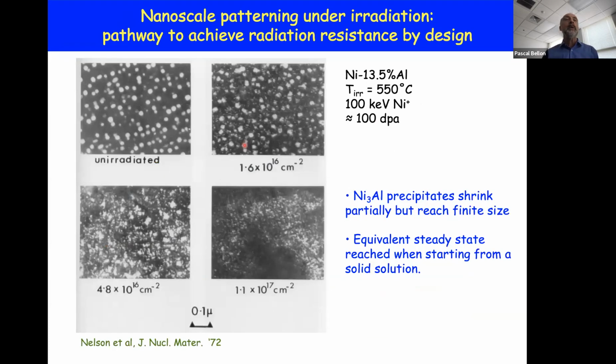And so to illustrate what we mean by self-organization, here's one of the first demonstrated examples of self-organization in an irradiated alloy. That's from the work of Nelson and co-workers. You can see it's 50 years old already, so it's not very recent, but nevertheless, there's a lot of intriguing science around it, as I will show you. So in this case, this is a gamma-gamma prime alloy. So we have in bright contrast, in dark field mode, these gamma prime precipitates in a nickel-based alloy. And these precipitates have been prepared by the appropriate heat treatment.